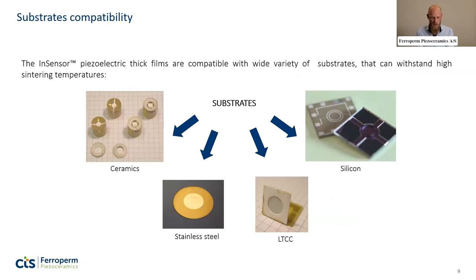So these are some of the substrates that we've tested in the past, and of course I mentioned the silicon MEMS substrate, but we also have ceramic substrates. We try to print on LTCC, low temperature co-fired ceramics, and even on stainless steel. And of course, the requirement for the substrate is that it has to withstand the firing temperatures that the thick film is seeing. So that's temperatures up to 800, 900 degrees C, meaning that that's the kind of durability requirement for the substrate. Steel is right on the border, so some applications might not be well suited for steel, but anyway, this is where the limitations are and the opportunities.